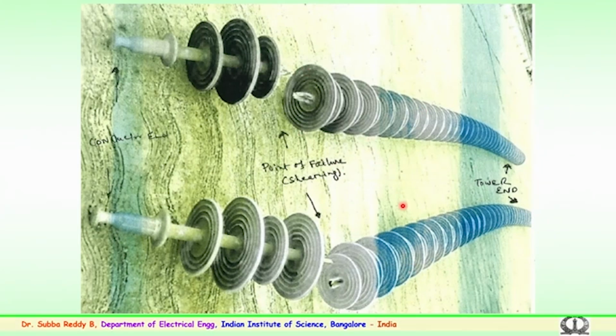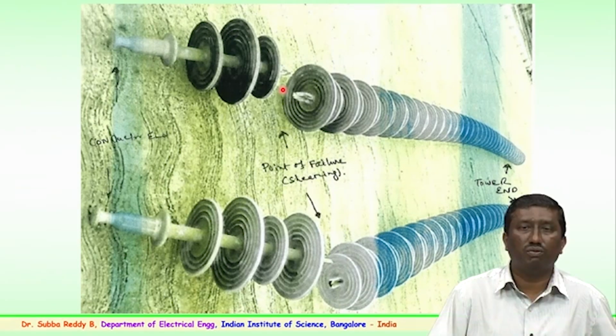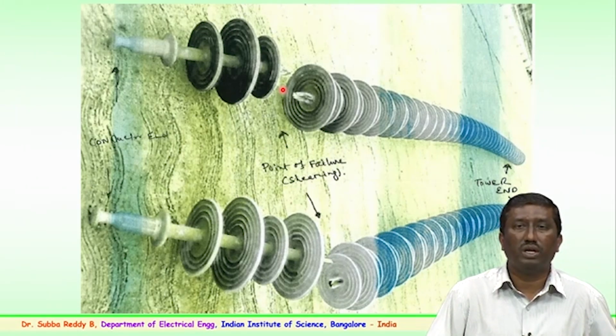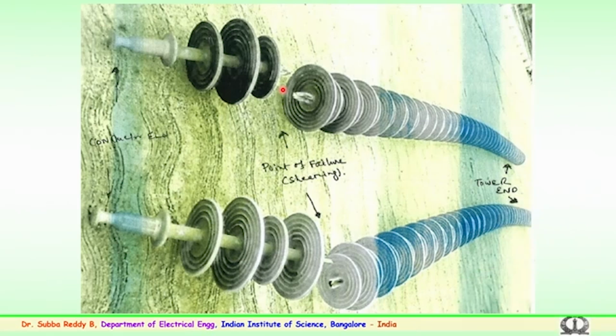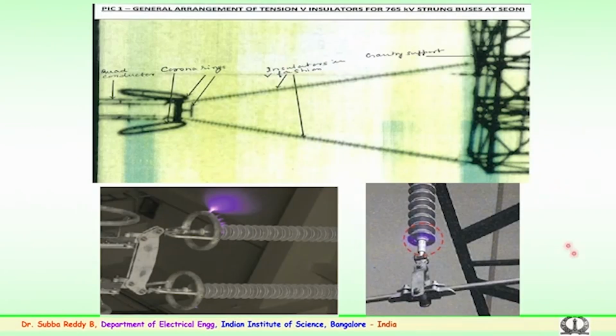This is particularly for one transmission system, a 765 kV line, where the tower failure happened 8 to 9 months after the erection. So, a very serious concern. Once the technology which you are adopting has to be carefully looked at, equal importance must be given not only to the material and the newer technology, but to how it is used, how it is erected in the field, and what the orientation of the corona control rings is. This failure was caused by the placement, design and orientation of the corona control rings.